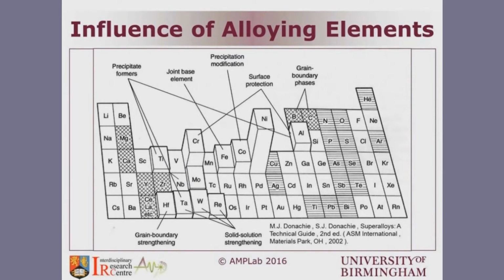The following slide is probably just to further strengthen the previous point. It shows what role the alloying elements play in terms of the performance of nickel superalloys. So some elements are used for oxidation resistance, some are used to control the precipitates and their types, and some others like tantalum, tungsten and rhenium can be used for solid solution strengthening. But overall, if we're dealing with an alloy class that attracts at least a dozen alloying elements, you would expect that this will become rather complex when you look into its processing by any manufacturing technique.